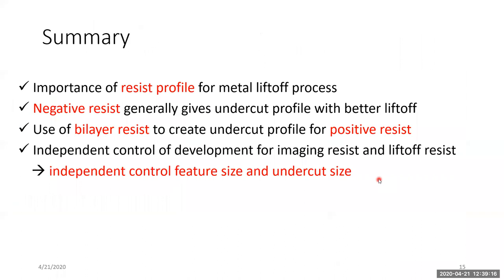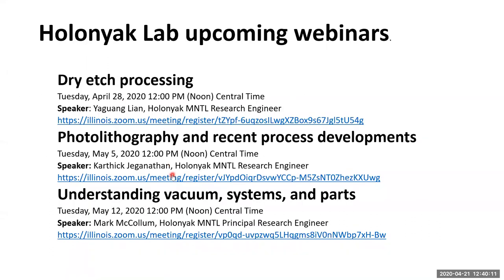In summary: resist profile is critical for liftoff, especially for positive resist. If you have the choice, negative resist is generally better for liftoff. For scanning lithography or other situations requiring positive resist, you can create an undercut profile using bilayer resist. Finally, using completely incompatible developers for the imaging resist and lift off resist gives independent control of feature size and undercut size. Our next webinar is next Tuesday about dry etching at the same time.